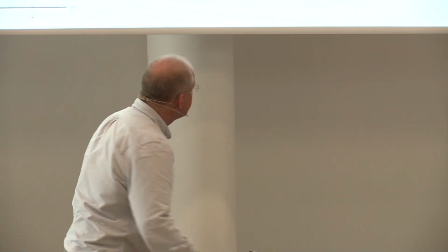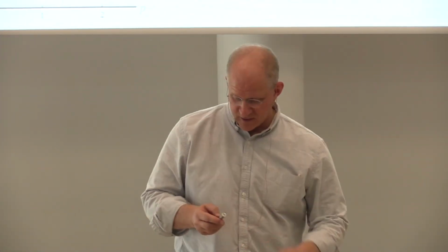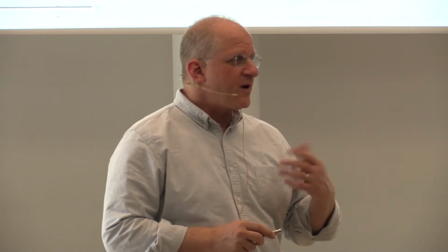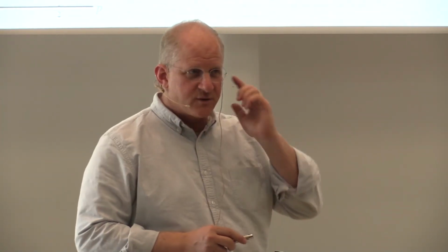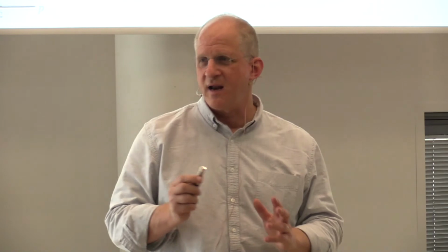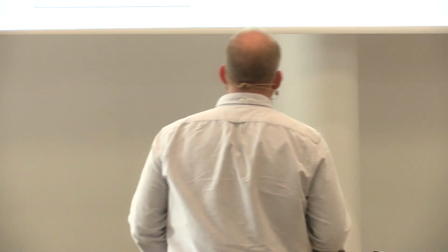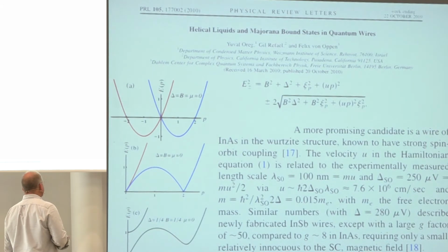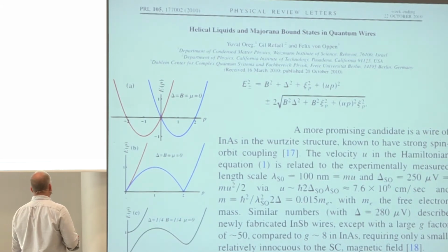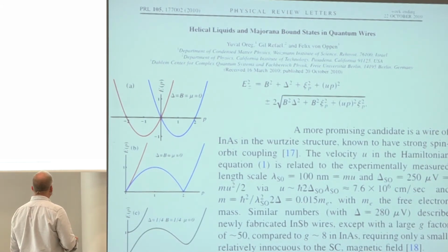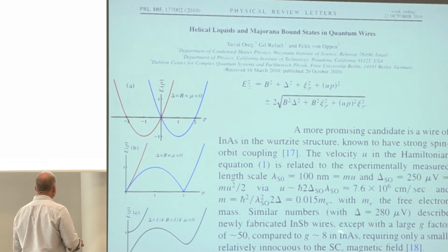Okay, so we were given a lot of information by these analyses of whether or not the parameters of these particular materials were sufficient to reach the regimes that were predicted. And we wouldn't have even started down this experimental road had we not had enough calculations and enough experimental information about the effective mass, the spin-orbit coupling, the G factor of these semiconductor nanowires that produce these one-dimensional materials.